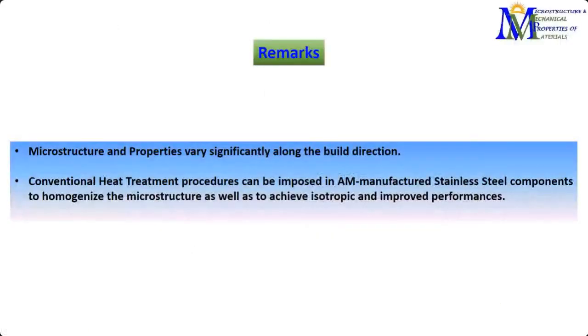The takeaway note is that overall, in metallic systems, there is a huge difference in the microstructure and the properties. There's an anisotropy along the build direction, and conventional heat treatment procedures in stainless steel components can actually lead to further homogenizing the microstructure as well as achieving isotropic and improved performance.